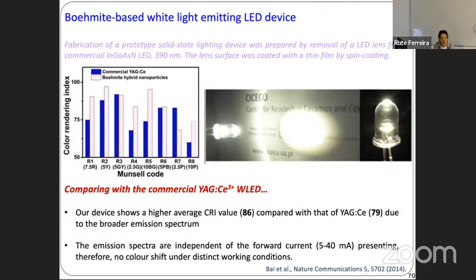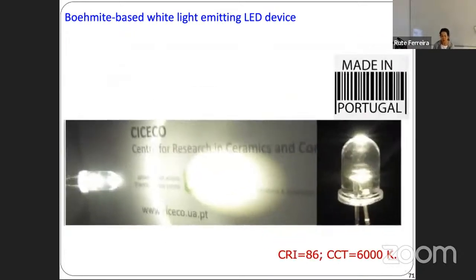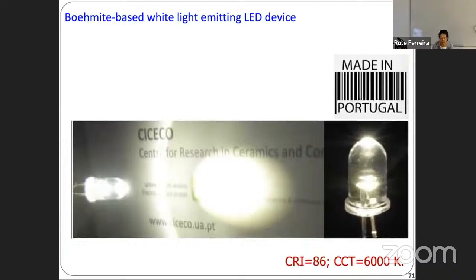In fact, our device shows a higher CRI value, 86, compared with that of the commercial one, 79, due to the broader emission spectrum. And another important aspect is that since we are using a single white light emitter, not the combination of blue and green, or blue and yellow, this means that emission spectra are independent of the forward current, presenting therefore no color shift under distinct working conditions. So our optimized device displayed a CRI of 86 and a CCT value of 6,000 Kelvin.